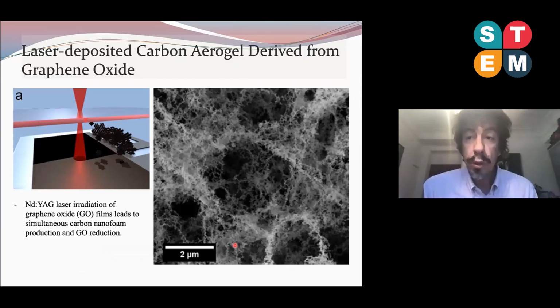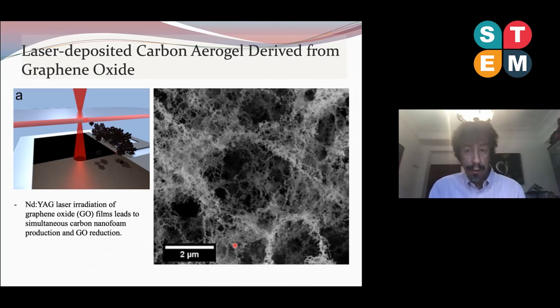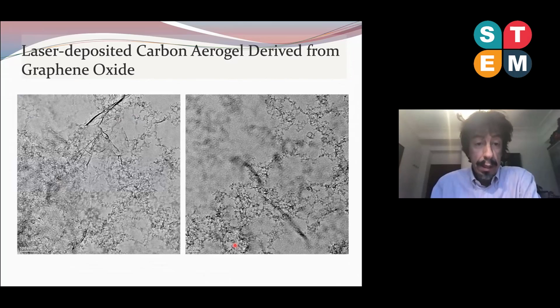And finally, I'm going to show you some more of our latest results on carbon foam production by laser ablation, but instead of using organometallic complexes, this time we tried a different substrate, which is graphene oxide. So we irradiated graphene oxide and we observed the formation of this foam-like material. And these are TEM images that show this rosary-like assembly of very tiny nanoparticles of carbon foams, carbon aerogels.